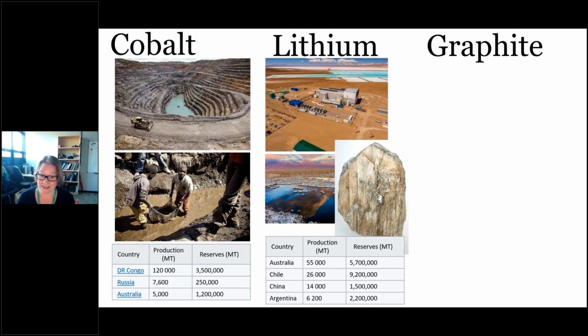Now, currently, over 50% of the production of lithium actually comes from Australia, from the spodumene rock, and about 25% from Chile from those salars that I spoke about. But as you saw in Europe, in 2020, we were still sourcing most of our lithium from South America. And again, considerations around biodiversity areas are really key here. A lot of the places in South America are in areas where there are protected species. One of those, for example, is flamingos in some of those areas.